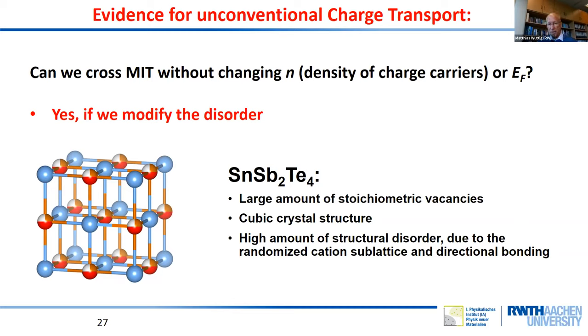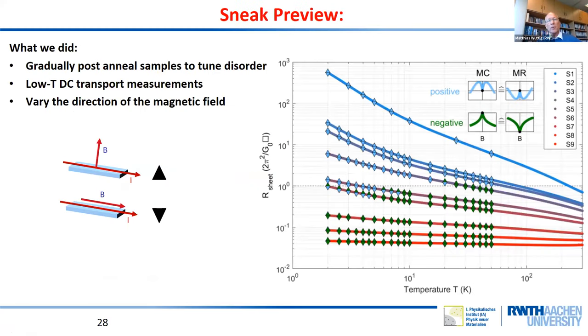So now we can take such a crystal in the form of a thin film and heat it to different levels of the random arrangement of vacancies. And with this, we have a number of different observations. Once again, we take these films, we heat them to different annealing temperatures, and therefore we tune the disorder. And then we measure the sheet resistance of these films. It's in principle the same film heated to higher and higher temperatures, so there's an irreversible ordering of the sample.